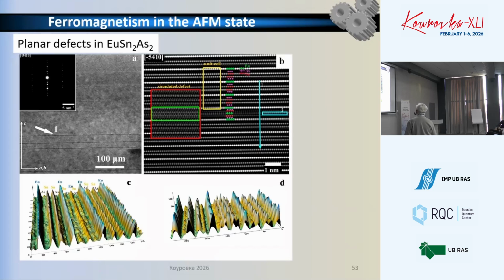And what is specific here in this defect. The distance between the europium layers, the white balls, is 20% lower. The profile also shows that inside the defect layer, there is an additional weak but still additional row of europium atoms, which are sitting not at the same distance to the electron beam, somewhere further away. And the most remarkable thing is that the tin atoms are missing here. And nothing changes with the arsenic.